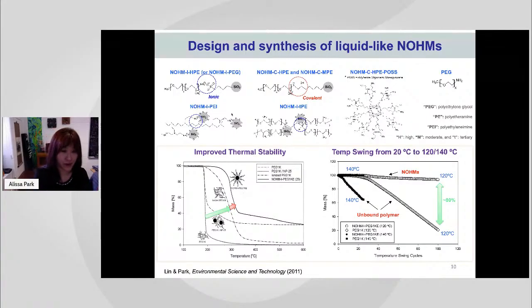If you look at the bottom left figure, as we expected, the thermal stability of NOHMs, which is on the most right-hand side, is a lot better than the starting material, which is on the left-hand side, the untethered polymer. And this is only once, but if you look at the right bottom figure, this is the long-term stability of NOHMs versus the untethered polymer that we started with. After 100 cycles, NOHMs maintain pretty well in long-term stability, but 80% of the polymer we started with degraded. So in order for carbon capture technology to be economical, we should be able to recycle these materials hundreds and thousands and tens of thousands of cycles. So this figure shows that although polymer with functionalized amine can be a really great material to capture CO2, it is not in the long run. So making NOHMs out of these polymers is really beneficial.